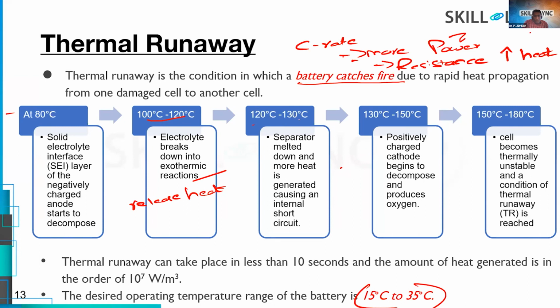And at 120 to 130 degrees, the separator melts down, and more heat is generated. You can see there is a separator, right? The separator is the plastic membrane which separates the anode and cathode electrodes. When it melts, the anode and cathode meet, so it creates an internal short circuit. So what does a short circuit do? More heat generation.